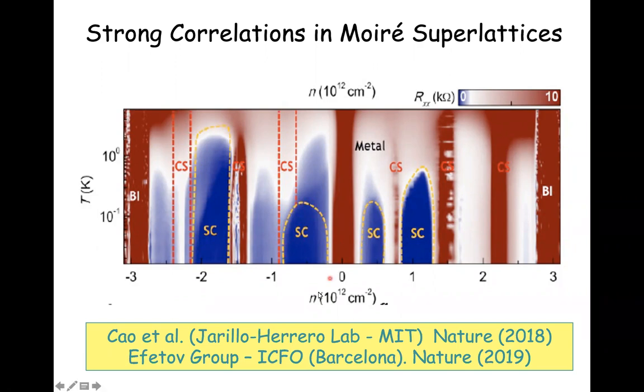I think this actual data set is from a follow-up experiment by Dmitry Efetov at ICFO in Barcelona. And one of the things you can see here that's rather amazing is that in this 2D system, you go from an insulating state in this dark red color to a superconducting state in blue with a change of electron density of around 1 in 10 to the 11 per square centimeter, or around 1 for every 10,000 actual carbon atoms in this system. So this is probably the lowest electron density superconductor in nature.